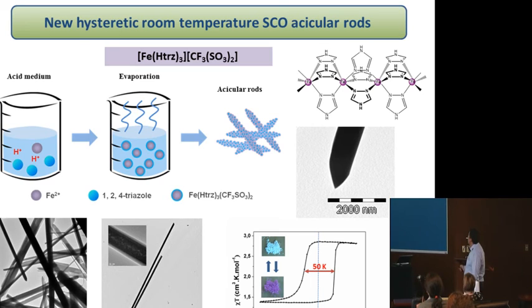This is another experiment. If you want to go towards applications and you use surfactant polymers, this can be a problem, because you have to remove the polymer and surfactants. So we also developed a synthesis without polymer and surfactant. Here you just adjust the pH. Using acid, it was possible to limit the growth of the particles, and we obtain these rods. So playing with the experimental conditions as a strategy, we can obtain different sizes, but also different shapes of particles. This is important, for example, for electrical measurements, and to try the dielectrophoresis method, it's necessary to have long nanoparticles.